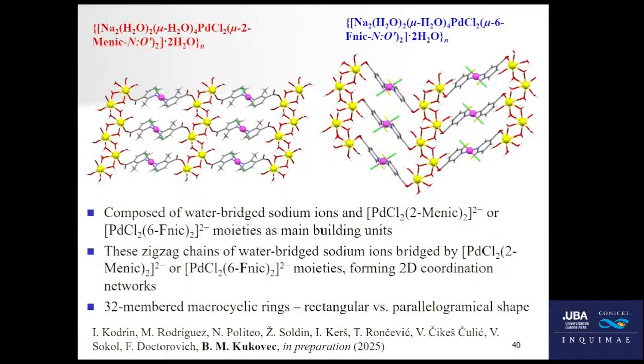So in the case of the 2-methylnicotinic and 6-fluoronicotinic acid, we get the same structural pattern. So I'm not going to repeat it because I just explained it, but what's the difference here? If you look at this macrocyclic ring, between this part of the chain and this part of the chain, here and here, in both cases it is a 32-membered macrocyclic ring, but in the first case this one is more like a rectangular shape, and this one looks more like a parallelogram. So that's the first and striking difference that you can see when you look at it.